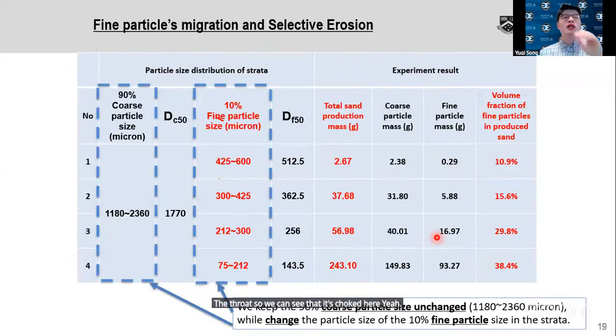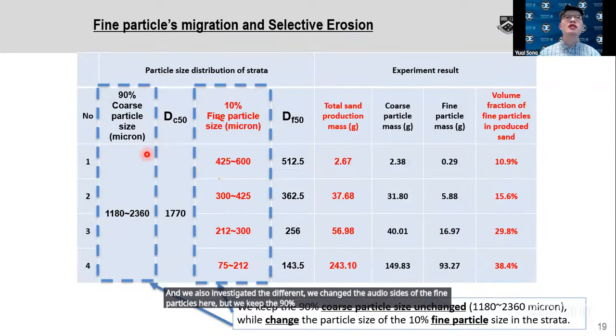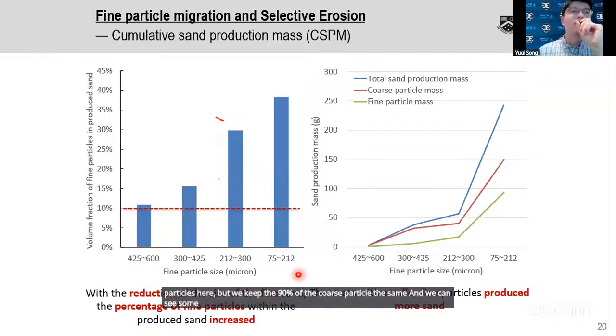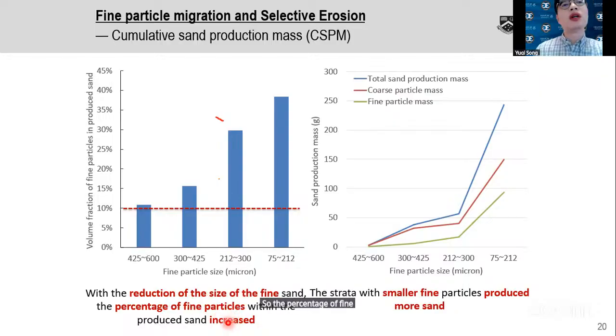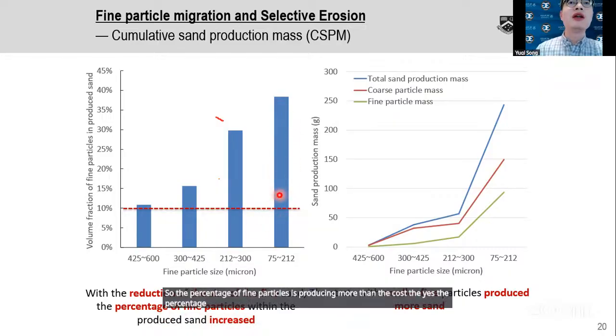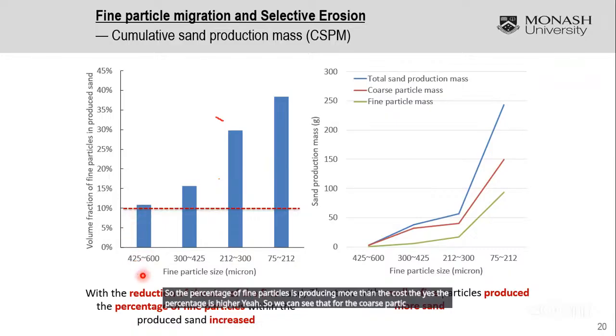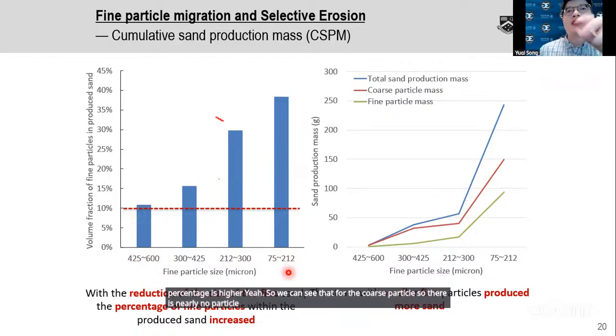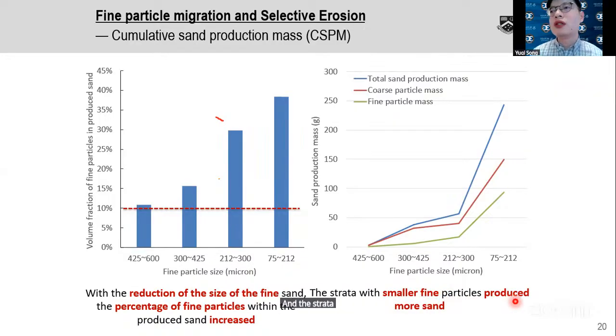We also investigated different cases where we change the particle size of the fine particles, but keep the D90 of the coarse particles the same. We can draw some conclusions. The first is that with a reduction in the size of the fine particles, the percentage of fine particles produced is higher than the coarse. For the coarse particles there is nearly no particle migration, but for the fine particles, at 75 to 212, great particle migration is observed here. The strata with smaller fine particles produce more sand.